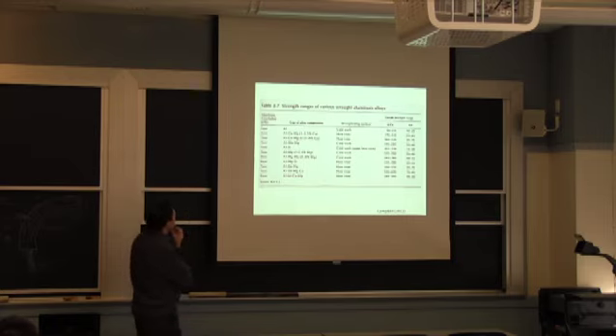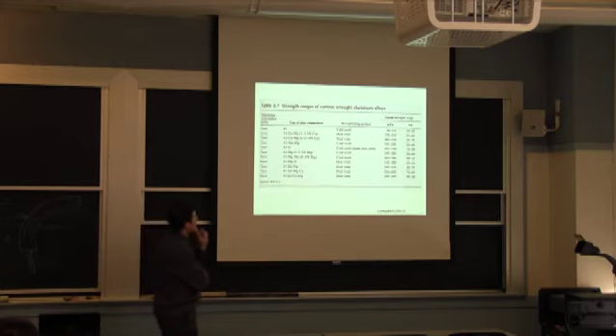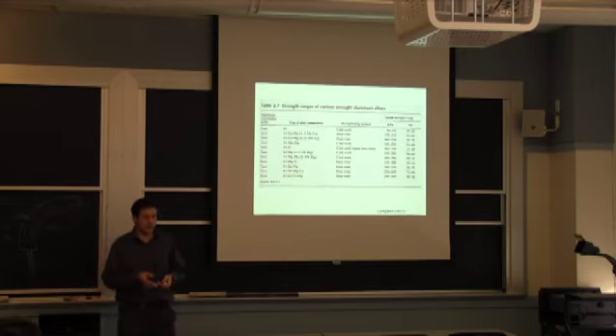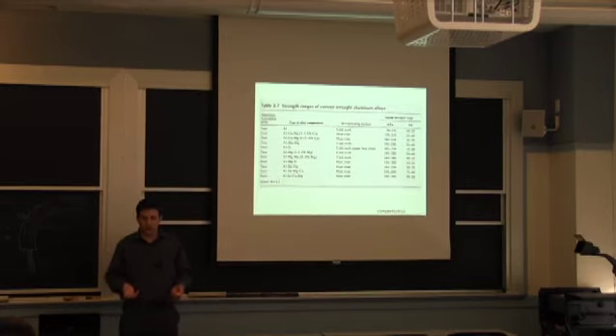The different series here, this 2000 series is fairly well known in aerospace, has copper in it. The idea for that is to put the copper in solution with the aluminum. Both aluminum and copper have the same crystal structure, so at high temperature, you can mix them together. And when you cool, if you cool fast enough, you're going to prevent the formation of other phases in the material. You keep it at what we call a solid solution. So that's quenching.